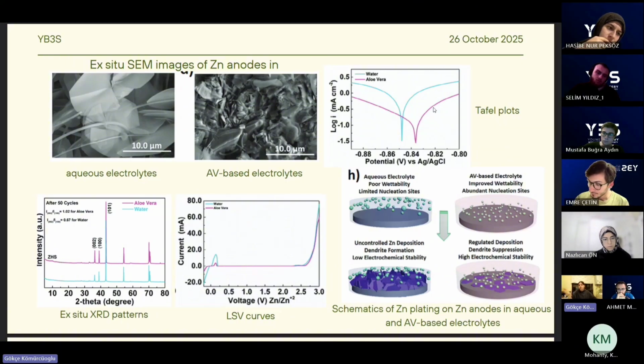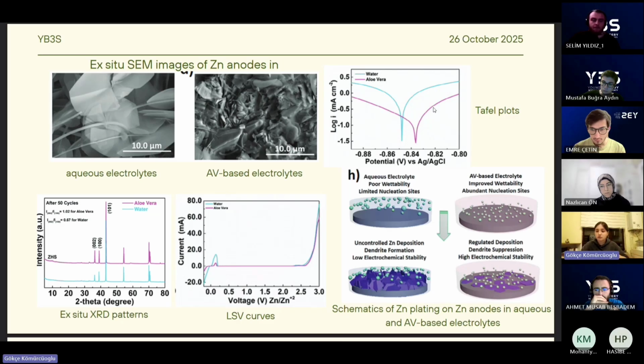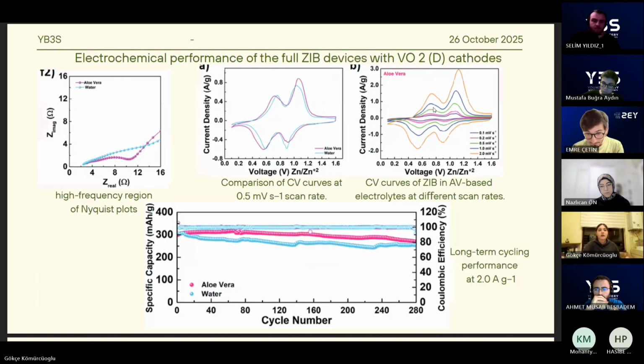a schematic for what I was telling. The zinc anode in zinc ion batteries, the dendrites happen to be hexagonal, as you see in the schematic, and they can also create spikes by piling up. On the right we see the aloe vera-based electrolyte, and it is more regular than the aqueous one.